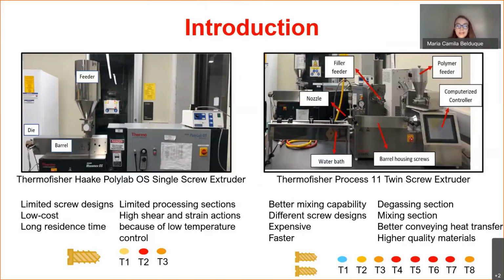Some of the essential differences between the two are the temperature control. In the single screw, there are 3 zones, which are controlled from a software. Therefore, you only have 3 stages to melt and extrude your material, which leads to high shear and strain actions in the material. In the twin screw, there are 8 temperature zones controlled from the touch screen of the computerized controller and a degassing section. This design results in a very convenient heat transfer and therefore material with higher quality.